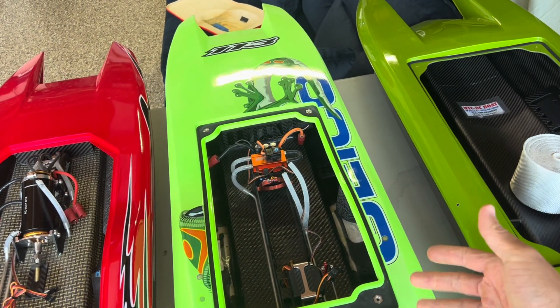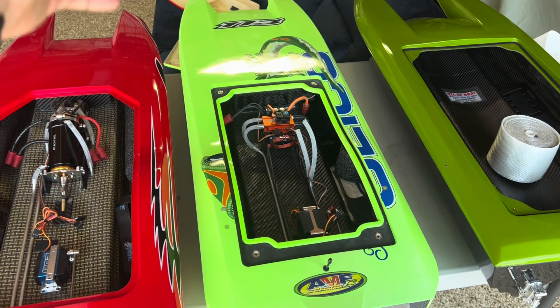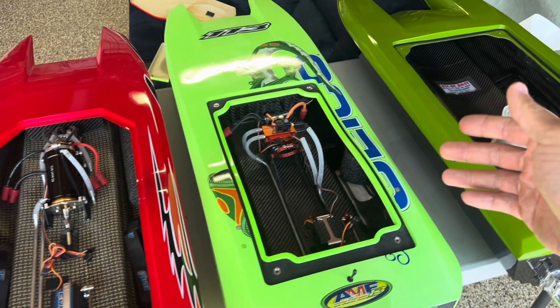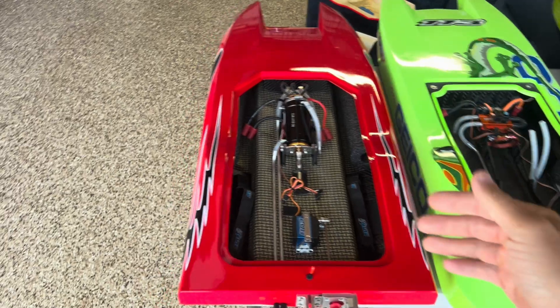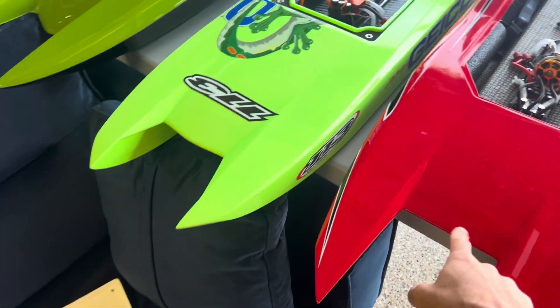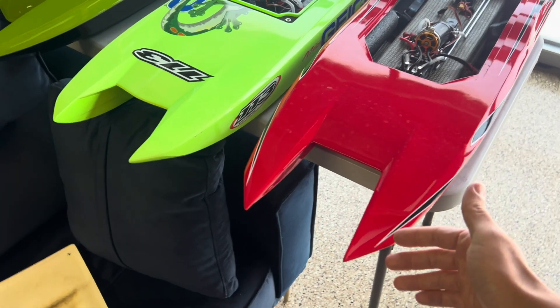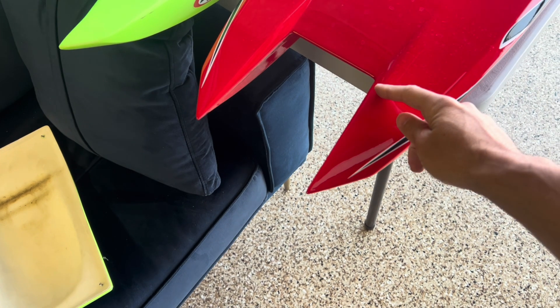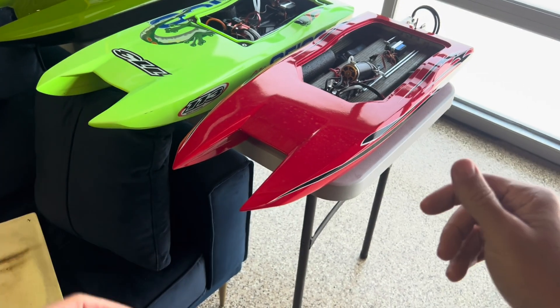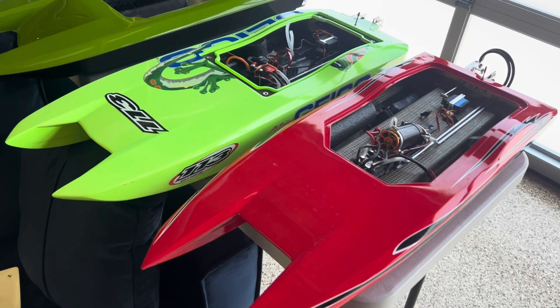Deck braces are a super simple way to reduce compression and tend to prevent blown seams. On a Geico or any Pro Boat product, I'd probably just do seam tape all the way to the end as far as you can, and I would pour the tips with epoxy and chopped carbon fiber — that's been done to all three of these boats. If a seam splits mid-hull you're probably okay, but if you blow out the entire front seam and the tips, that's much harder to fix. Pouring the tips helps the front end resist twist and keeps the seam from blowing apart.